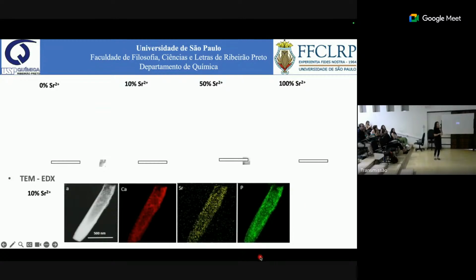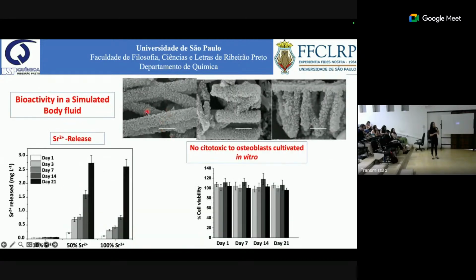But we show also that this nanotube, we added strontium to the structure of the nanotubes, and we see here in yellow that strontium was distributed homogeneously through the structure of the nanotubes, and we had no phase segregation. So we also prepared here material substituting calcium by strontium. These nanotubes were bioactive. I mean, after the immersion in a simulated body fluid, we precipitated selectively a hydroxyapatite at the surface, exclusively at the surface of the materials.